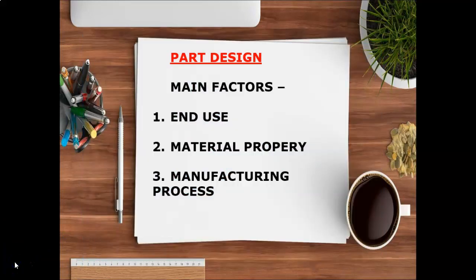In terms of end use, for example, if you want to design a living hinge for a ketchup cap, you need to choose the right material so that the cap can flex many times without breaking. You can choose either polypropylene or polyethylene because these polymers have low cost and ease of processing. PP and PE can flex a million cycles before failure, while many other plastics can only flex a few thousand times.